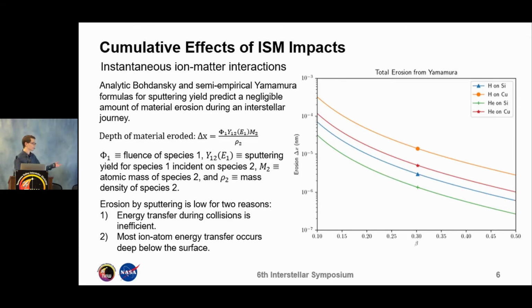M2 is the atomic mass of the target material, M1 is the atomic mass of the incident species, and rho 2 is the mass density of the target material. So this graph shows total erosion as predicted by this semi-empirical Yamamura formula. You can see that for silicon and copper, for journeys to Alpha Centauri with speeds between 0.1 and 0.5 c, the erosion is less than a single atomic layer.